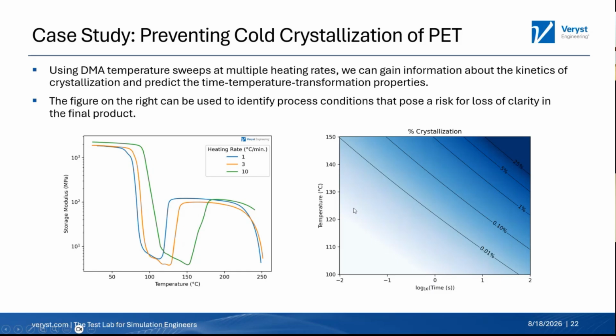Essentially, we're calibrating a model for the crystal nucleation and growth of the PET as a function of both time and temperature. And so you can use a diagram like this one on the right to help understand where the risks might be in your various processing conditions. So you spend a certain amount of time at 120 degrees C. This is in log time space, right? This is right about a few seconds at 120 degrees C, then you're at risk of getting about 0.1% crystallinity.